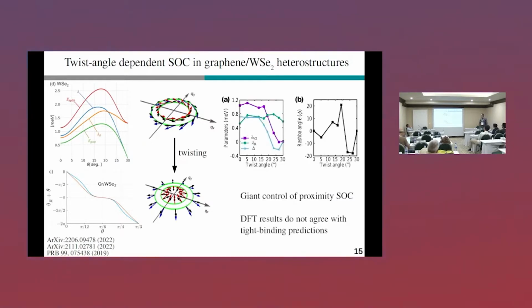Now, if you do actual DFT calculations on large supercells, you will find that the proximity spin-orbit coupling can indeed be heavily tuned, but the results do not completely agree with what the tight-binding picture says, because, for example, this valley-Zeeman spin-orbit coupling has here more or less a plateau and then drops to 0 at 30°.